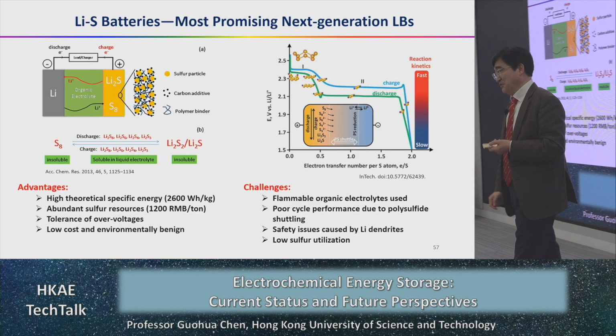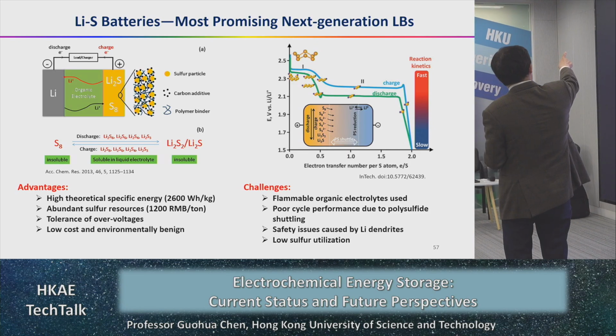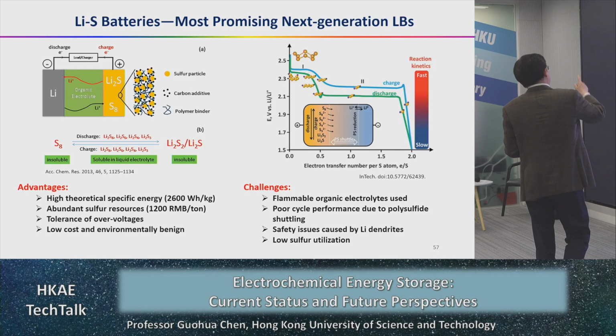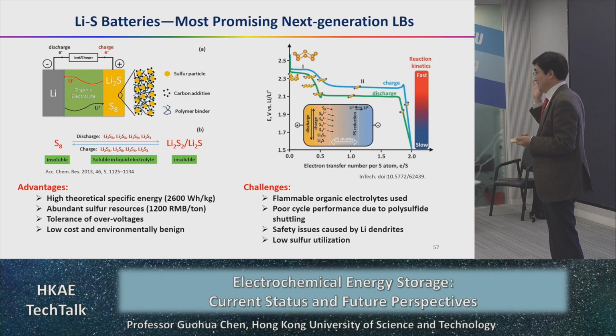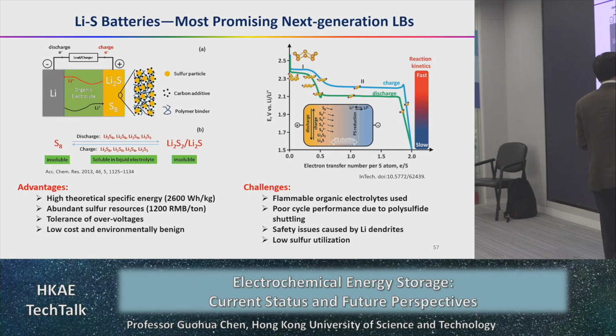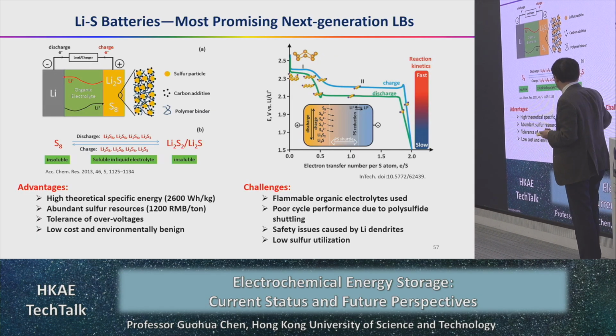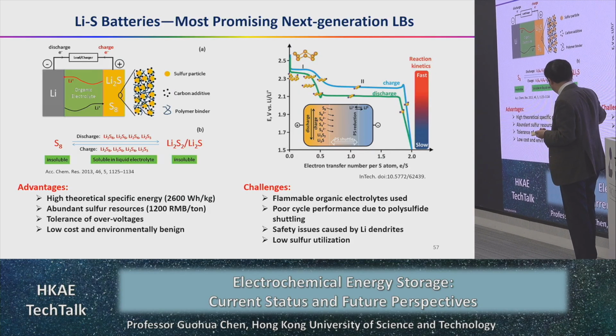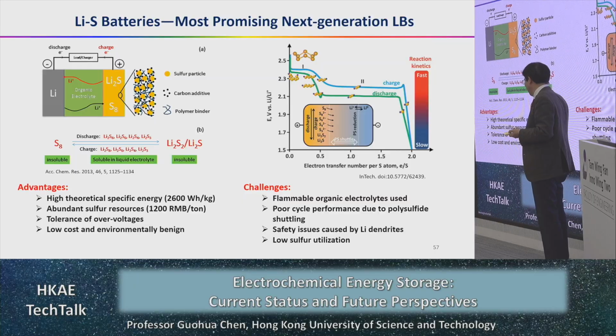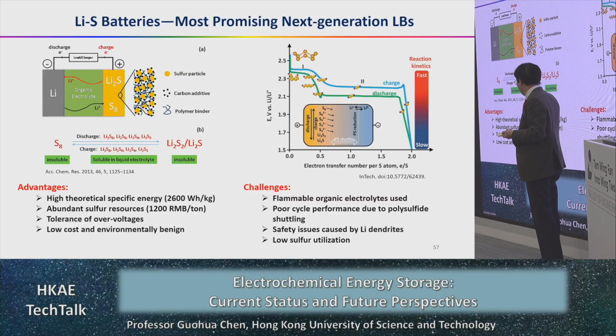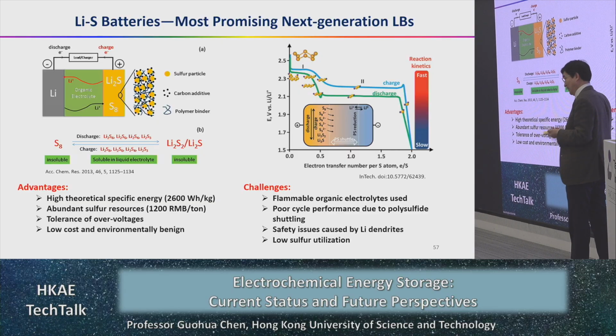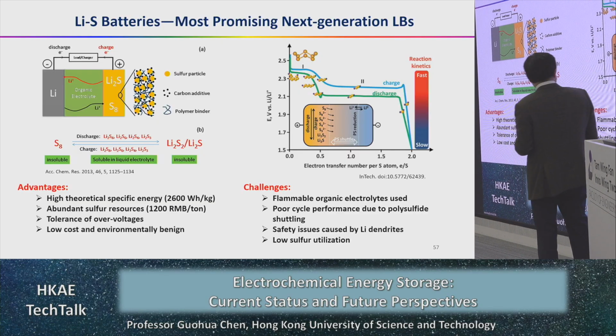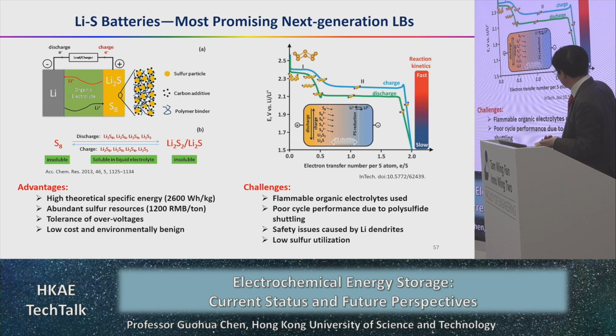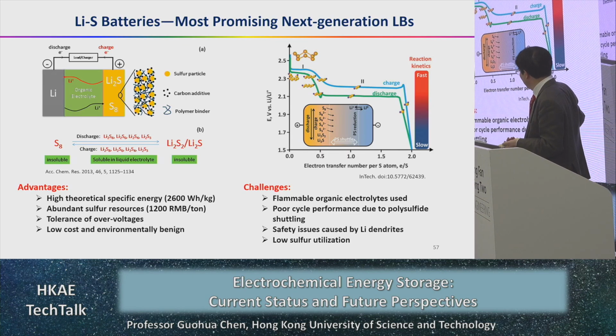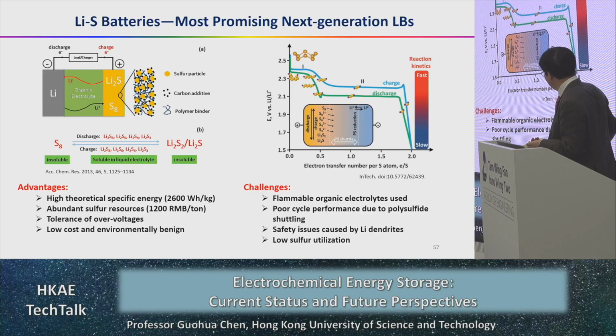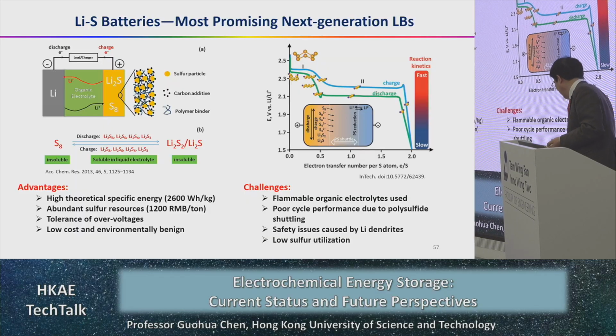So lithium sulfur, I must talk about this. This is the resurrection of the lithium metal, using lithium metal as the anode, sulfur as the cathode. It has very high theoretical capacity we're talking about, 2,600 watt-hour per kilogram. And also the sulfur is abundant, it's very cheap, tolerant of overvoltage, low cost and environmentally benign at this time, okay? And the fundamental problem we're talking about is the organic electrolyte used, a flammable one, and poor cycling performance and safety issue caused by the lithium dendrites.